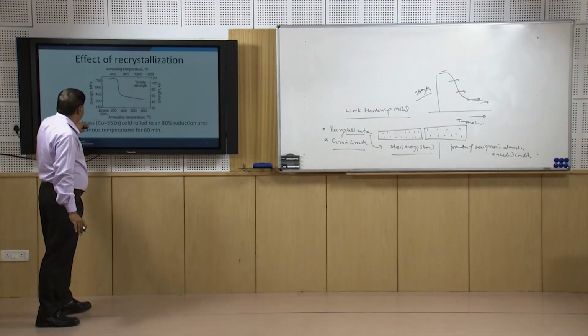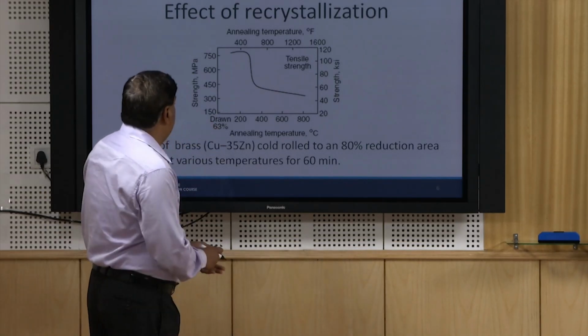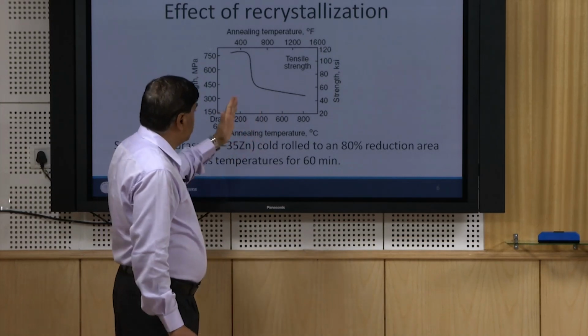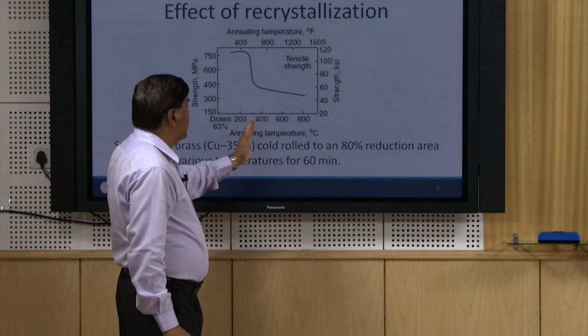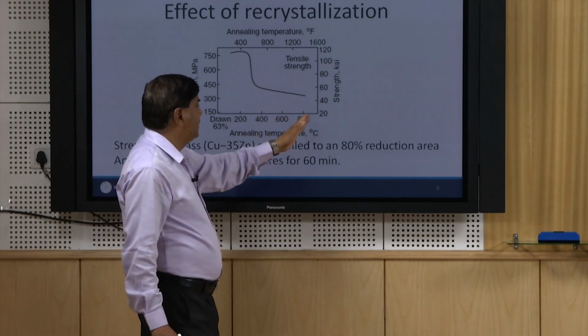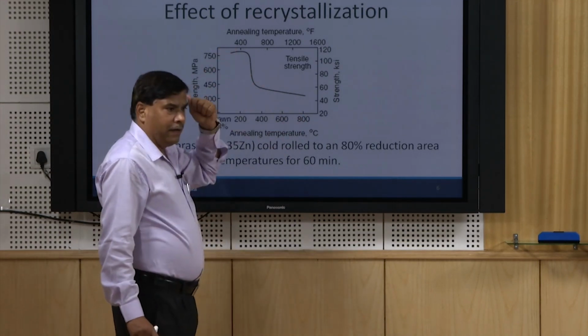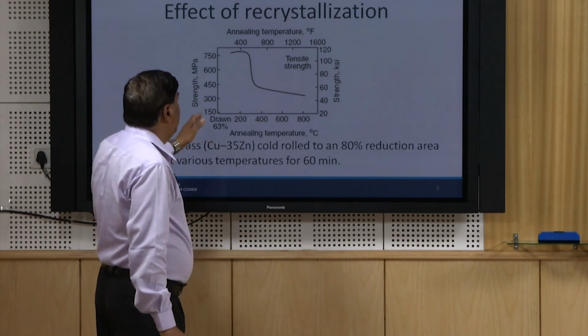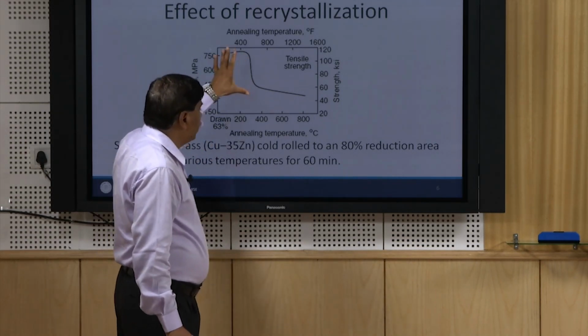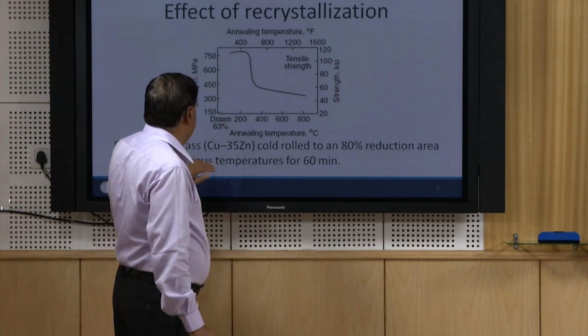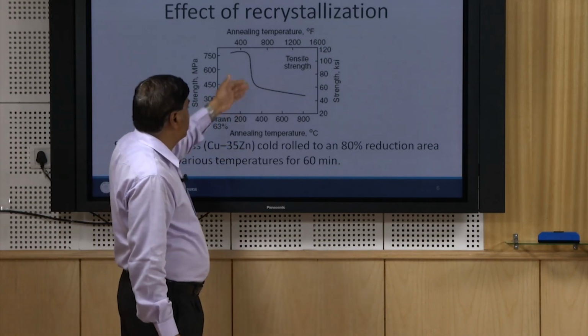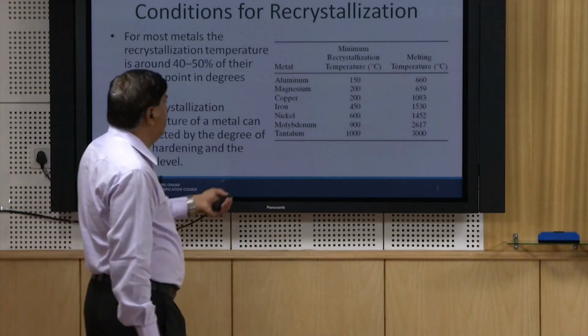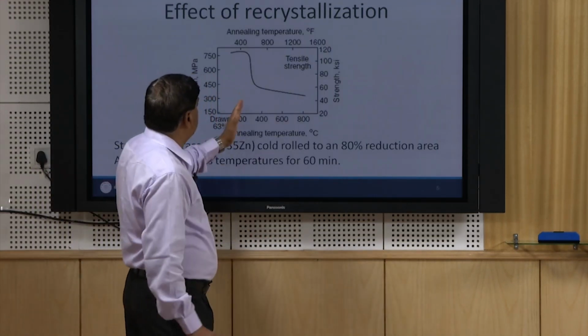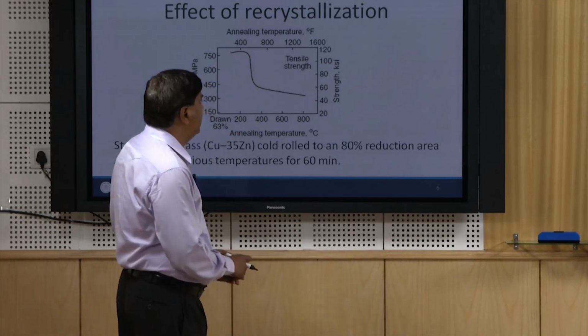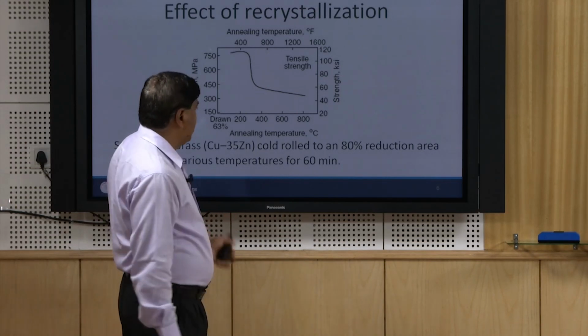Say for this example, the material cold drawn up to 63%, when it is given exposure to a higher temperature, say 200 degree centigrade, there is no major drop in hardness, but as the exposure temperature is increased to 400, 600, 800 degree centigrade, there is a sudden drop in the strength of the brass which has been cold drawn. This sharp reduction is attributed to the complete recrystallization occurring in the brass, since the recrystallization temperature for the brass is, as we have seen in the previous slide, 200 degrees centigrade. So, as soon as it is exposed, very quick and rapid recrystallization takes place, and this results in a significant drop in the strength of the brass as the exposure at high temperature takes place.